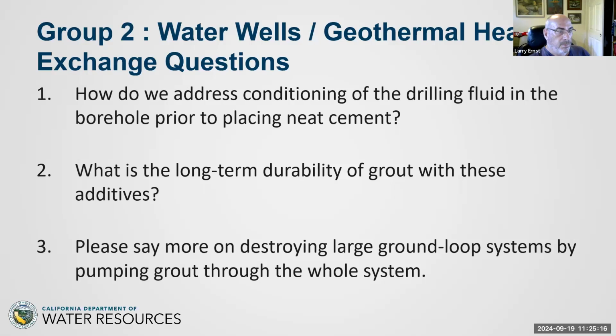Yeah. So therefore, physics is on our side there, Larry, in the sense that if we inject it at the right rate in the right place, and with the right composition of the grout, it should be able to displace upward, just like a piston from below. But the whole thing's going to be facilitated by an exchange to a lighter fluid to begin with. And also, is there a way of requesting a minimum annulus width even around the big casing? Well, it's funny, we keep going with bigger. In these particular cases, we're looking at likely having 6-inch annular spaces as opposed to smaller, just to facilitate accessory pipes and things like that. Sometimes even more, sometimes as much as 8 inches, to take into consideration injection pipes or other types of accessory pipes around the main casing.